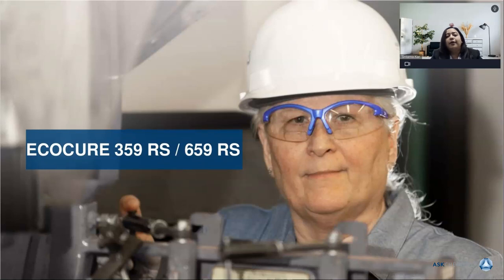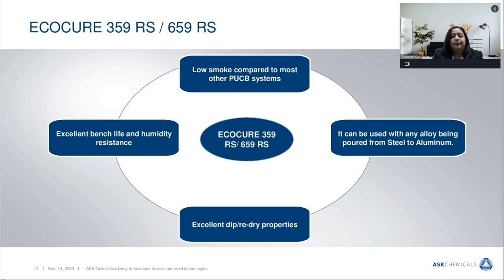So that was the story of our Isocure LR10, LR20. Now I'm going to talk about our second binder system, which is EcoCure 359RS, 659RS. This binder system contributes to very low smoke generation during pouring. It also offers great humidity resistance and excellent dip and dry properties with water-based coatings. EcoCure 359RS, 659RS was developed based on the KPI of a very low smoke binder to produce huge cores.